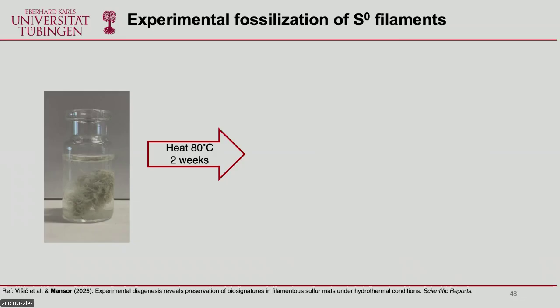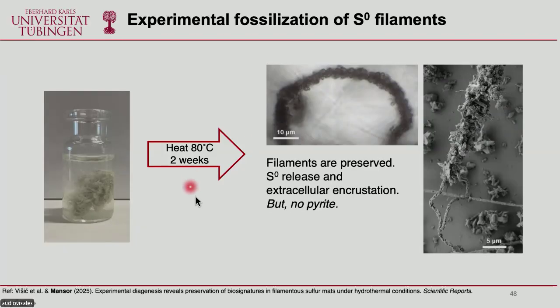So starting with the sulfur filaments, when we did this to the sulfur filaments, what we see is that the filamentous structures are in general preserved. They can have this encrustation of the minerals, but what's interesting is that they are not encrusted by iron sulfur minerals. They are encrusted only by elemental sulfur. And we think actually that this elemental sulfur is coming from inside the cells, being released and then precipitating outside the filaments. But there's no pyrite.